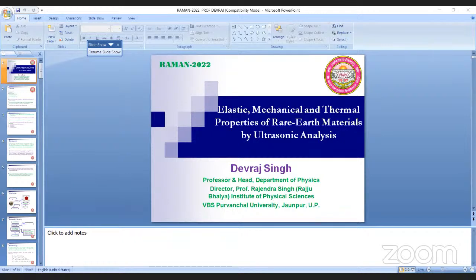Similarly, we can also obtain the ultrasonic velocity for these materials using the P wave, longitudinal wave and shear wave. So assessment of anisotropy behavior of thermal conductivity is also being done in this case, and this is higher for ErN than that of the ErAs. Thus, conductive heat losses will be reduced in case of ErAs along the 100 direction, which makes it suitable for potential application in the field of semiconductor.